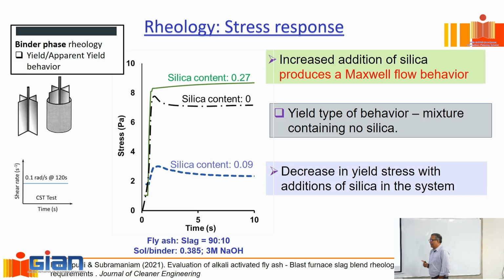Okay. Now, it took us a while to understand what is happening here. And the fact that this doesn't conform to this, that means this doesn't even look like this. Something fundamentally has changed. We look at this curve, what happens? It builds up to the peak and then it shears off here. Then it starts to flow, but then there's basically a decrease after this point, right? That's not happening here. What's happening? The resistance builds up to a constant value and it stays at a constant value, right? So when we started looking at this, we said that, well, this actually behaves like what we call a Maxwell flow behavior. And I'll explain this to you in the next slide. Whereas this is what we call the classical yield type behavior.